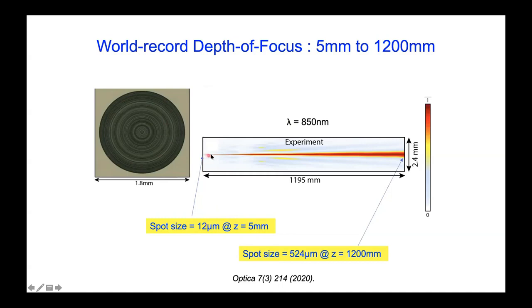But we wanted to maintain that focus as you move away from the lens. So we want the light to be very tightly focused all the way up to a little more than a meter. So this is, again, going from 5 millimeters away from the lens to about 1.2 meters away from the lens. That's a pretty incredible number, about 4 orders of magnitude larger than what one would expect from a diffraction-limited lens with the center focal length about there.